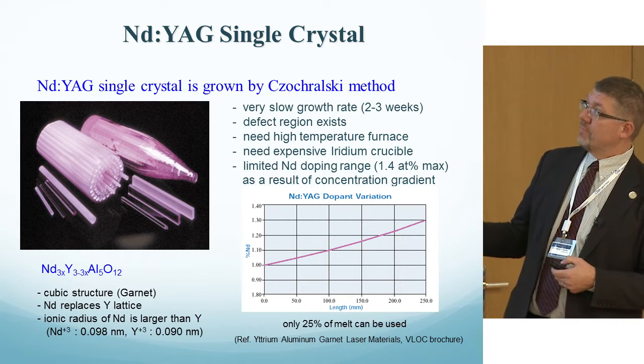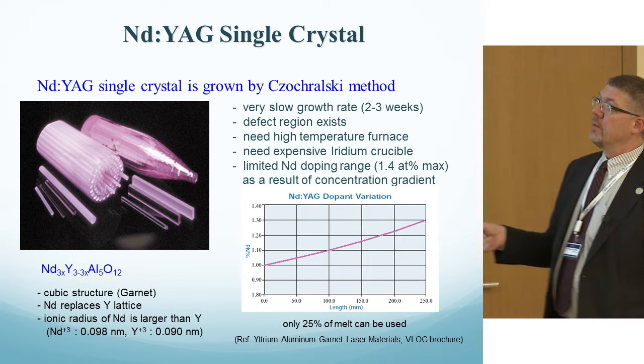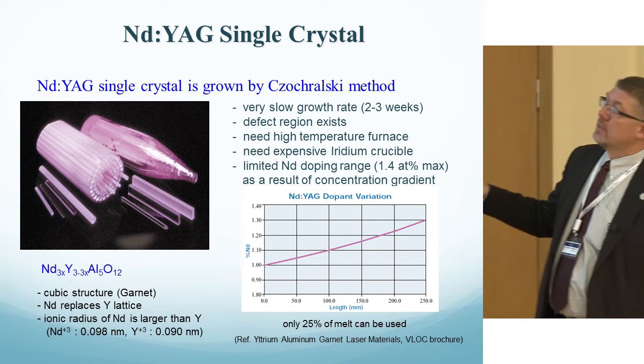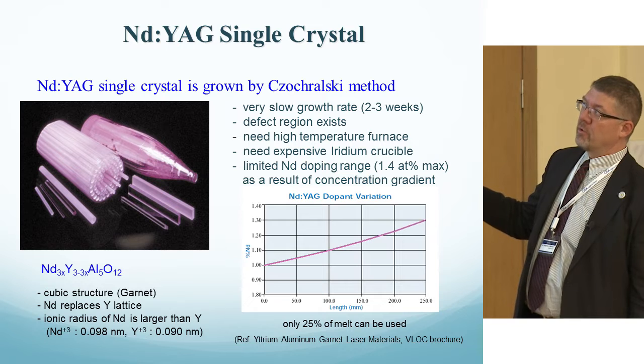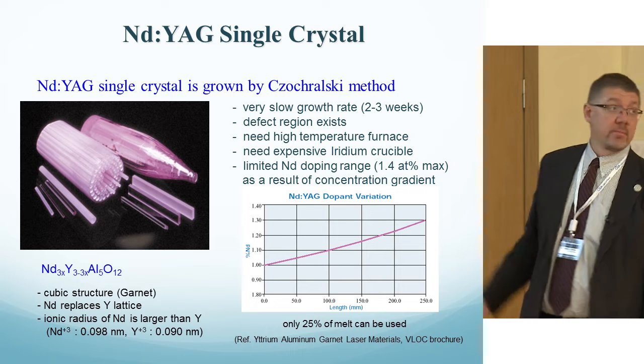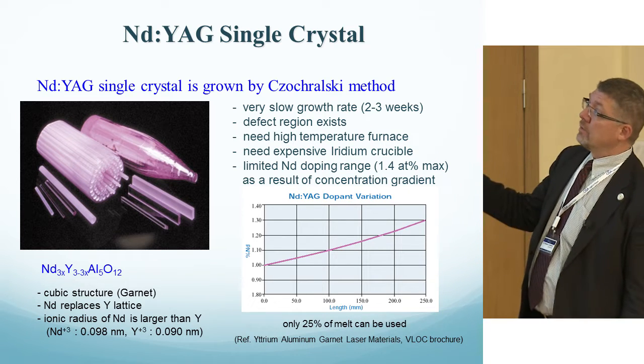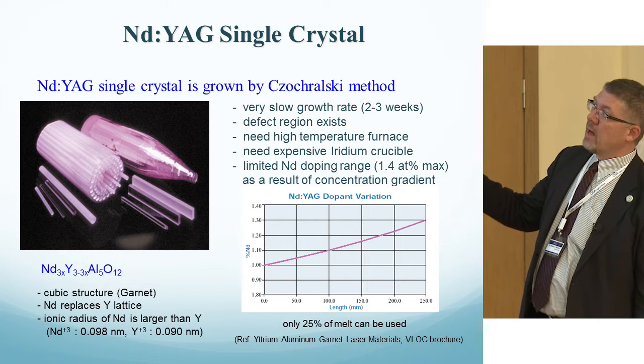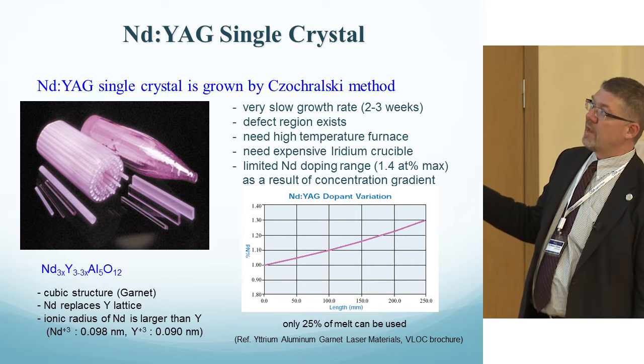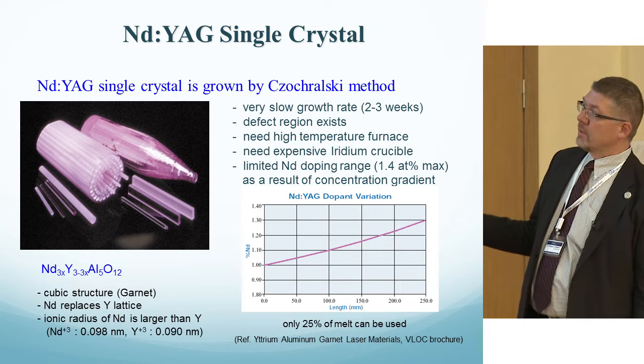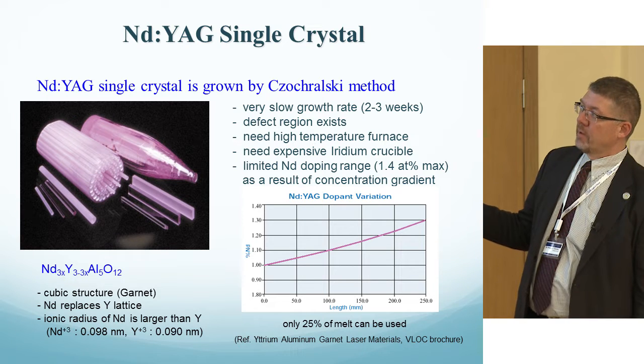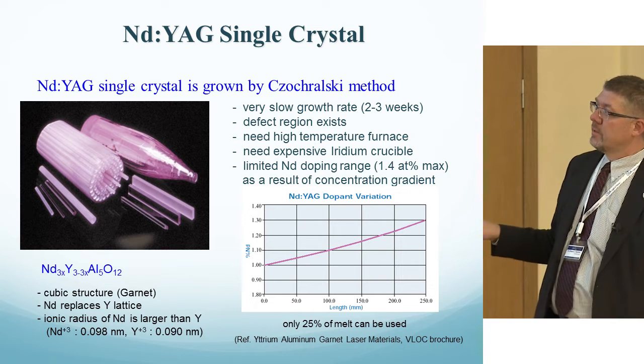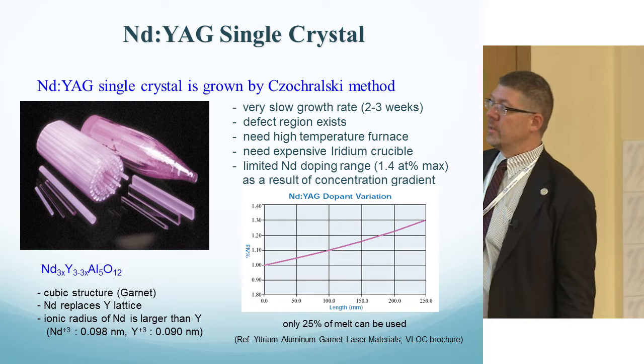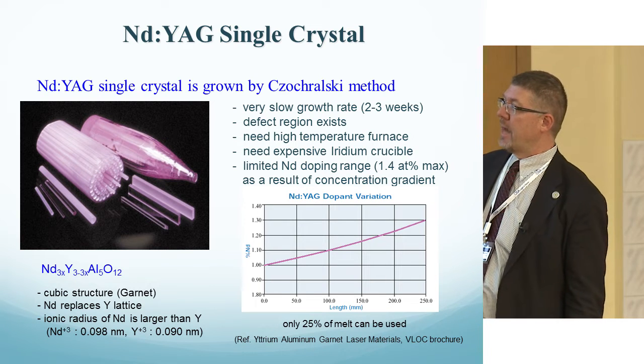When you talk about the largest single crystal neodymium YAG, if you look at this, this is right at 100 millimeters across and about 250 millimeters in total length. You can see where laser rods have been cored out with a diamond bit. There's also slabs that have been cut from here. The chemical formula, the neodymium ion, resides on the yttrium ion site. It's a garnet cubic structure. The neodymium, as I said, replaces the yttrium in the lattice.